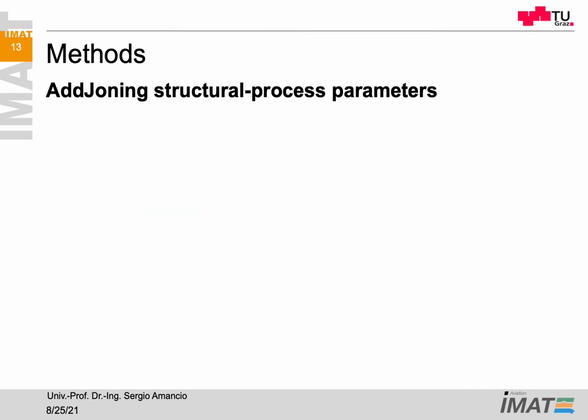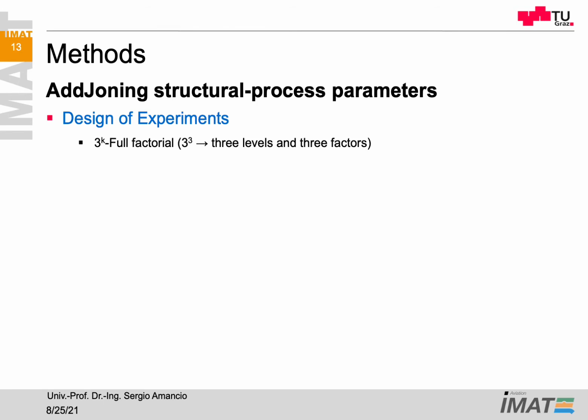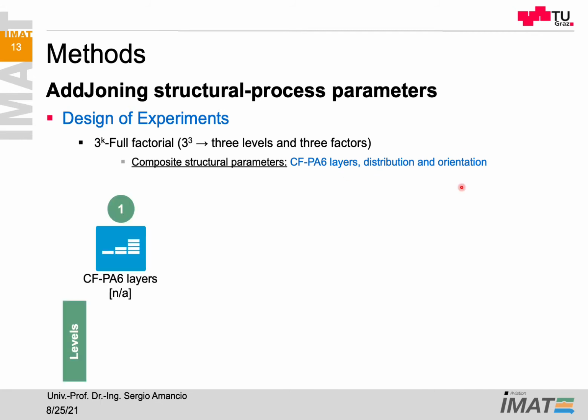So the AddJoining structural process were optimized and analyzed by design of experiments where we use a 3^k full factorial, so 3 levels and 3 factors, so 3 AddJoining parameters, which were the number of CFPA6 layers, so the number of carbon reinforced layers, its distribution, and the orientation. Such as like this is schematically represented, we work with 4, 6, and 8 layers.